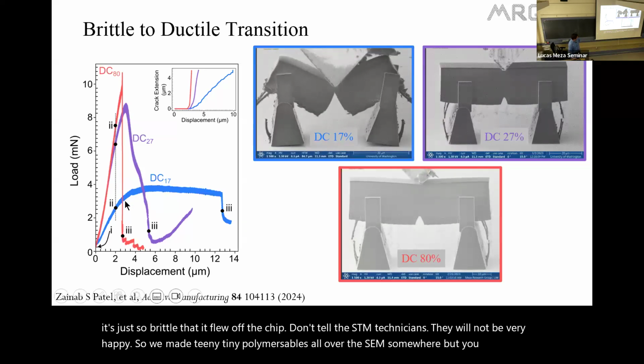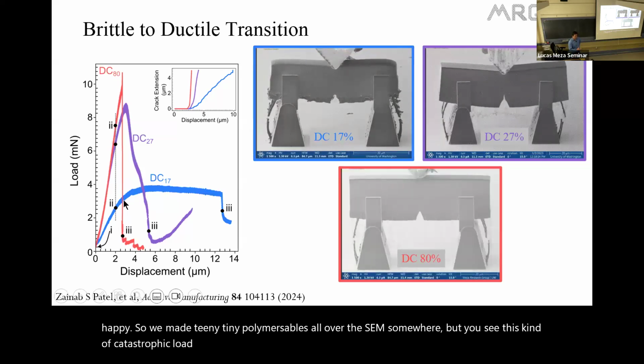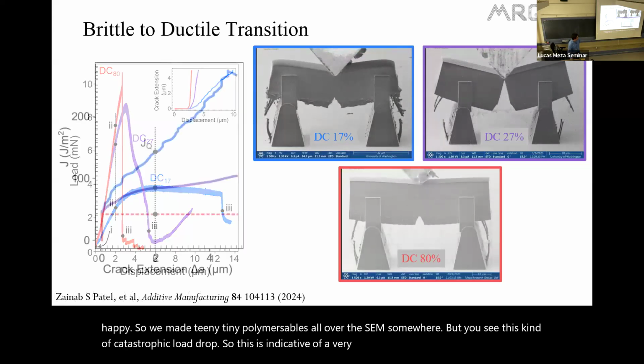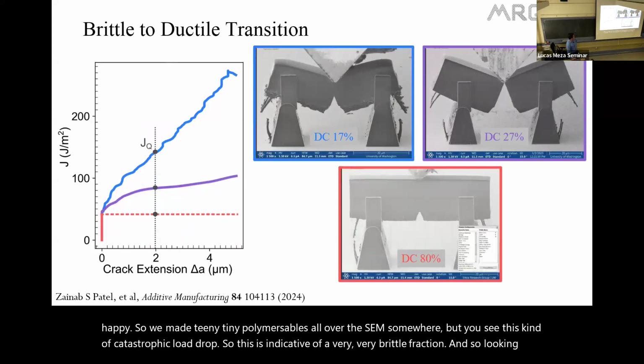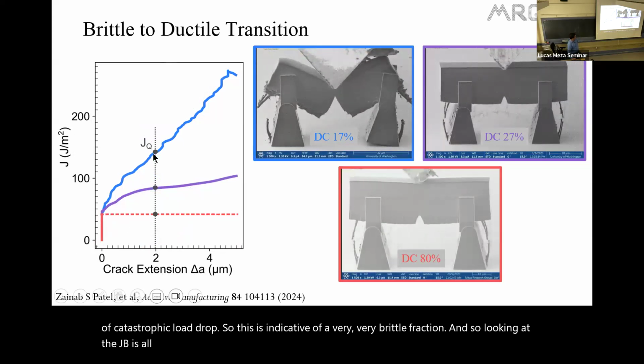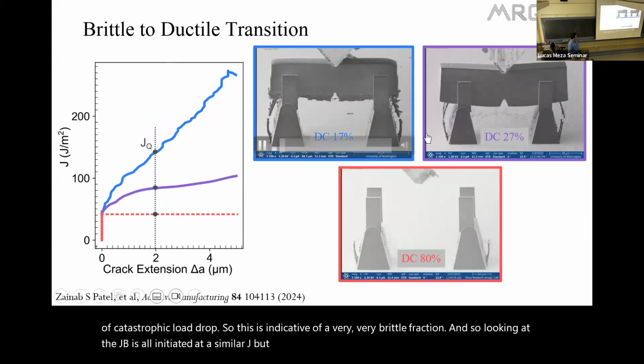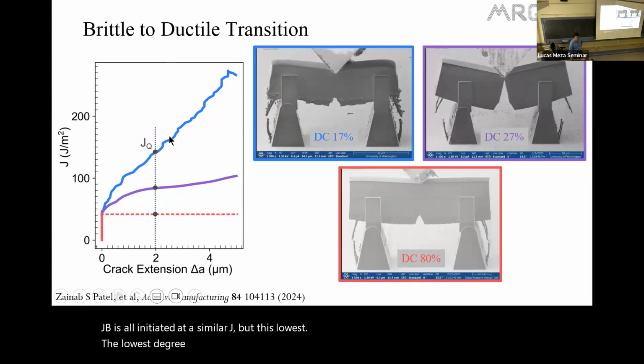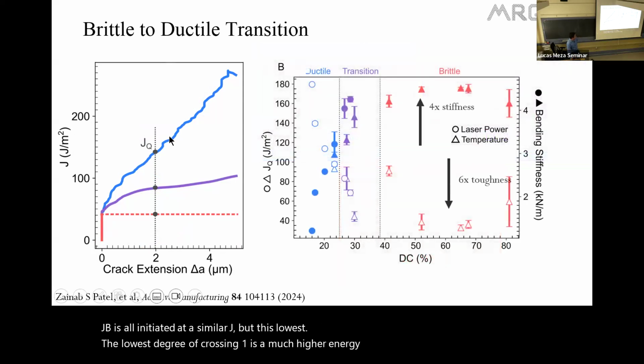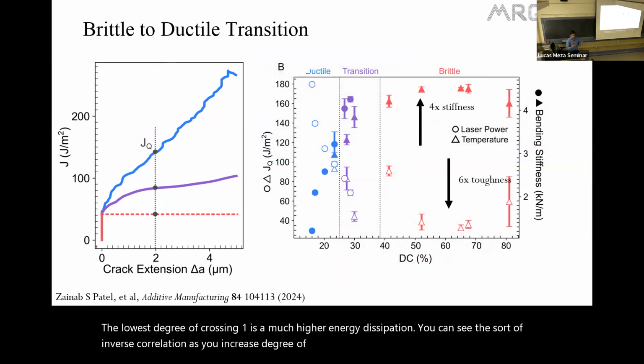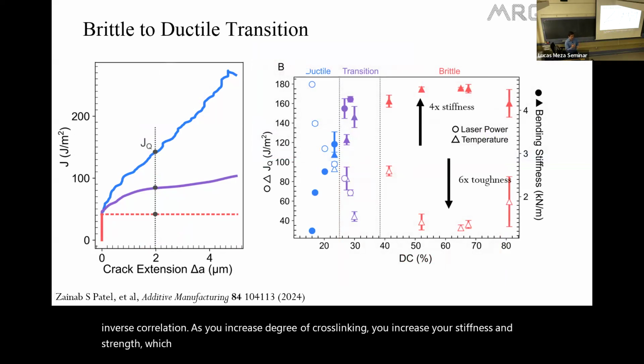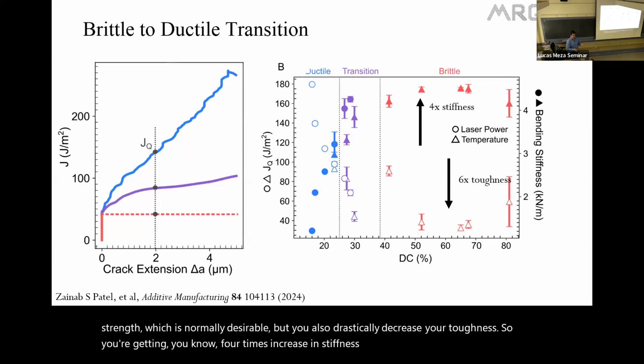But you see this kind of catastrophic load drop. So this is indicative of a very, very brittle fracture. And so looking at the J, these all initiate at a similar J, but the lowest degree of cross-linking one has a much higher energy dissipation. You can see the sort of inverse correlation. As you increase degree of cross-linking, you increase your stiffness and strength, which is normally desirable, but you also drastically decrease your toughness. So you're getting 4 times increase in stiffness, but 6 times decrease in your energy dissipation toughness.